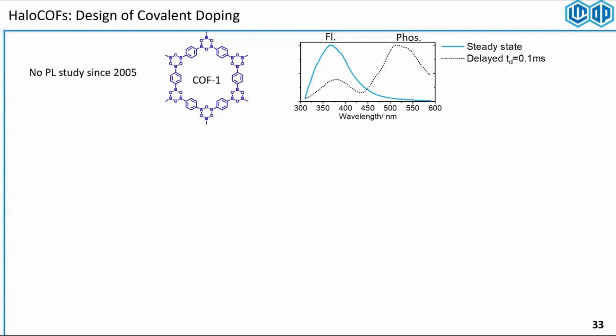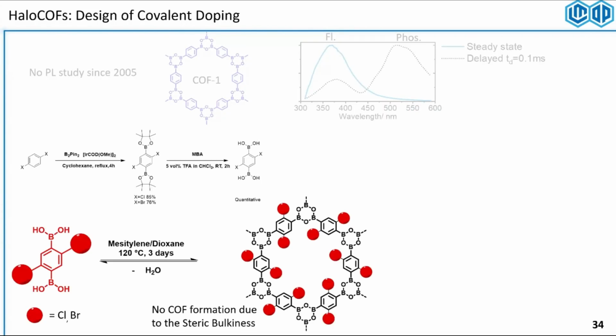So nothing interesting, so to say, about this. It's a fluorescent framework. But when we looked at the delayed emission, we found that it has a tiny, tiny bit of phosphorescence. You can imagine this peak being somewhere down here, this is normalized, right? Being somewhere down here in the background. So it had a little bit of delayed emission somewhere there that we could, in principle, enhance by adding something heavy into this framework, right? So I started designing the dichloro and dibromo version of this phenylene diboronic acid to see whether we can enhance the phosphorescence emission now through heavy atoms.